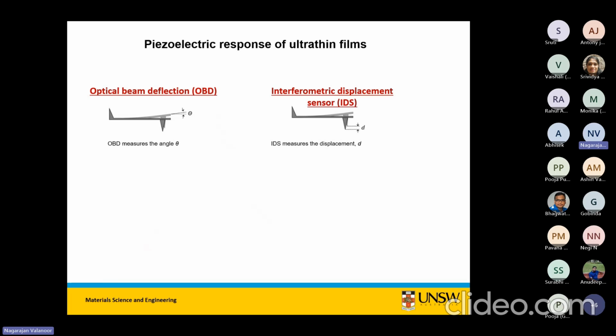If you want to measure the piezoelectric response of this film, we do PFM, but one of the problems was how do we separate the artifacts, because it's quite rough. So you have electrostatic contribution to the tip other than the pure piezoelectric contribution. So instead of using the optical beam deflection method, we use this method called an interferometric displacement sensor, which is something that Oak Ridge guys have developed with Asylum. So instead of having a laser beam that measures the angle on the detector, it actually measures the displacement using an interferometric system built inside the tube.